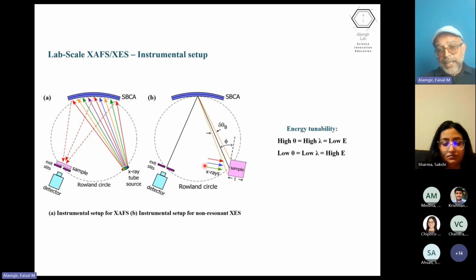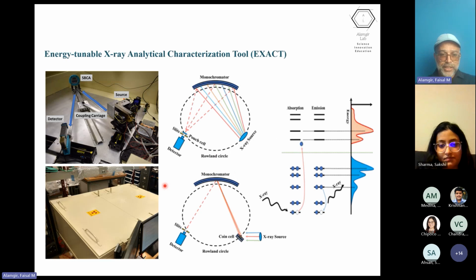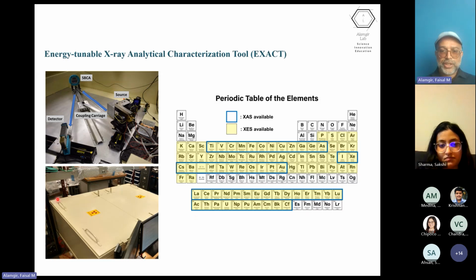Similarly, if we irradiate the sample directly with an X-ray source from the outside first, and then look at all the X-ray emissions coming out of your sample, we can use that same crystal to energy select the emissions coming from your sample, and then we can do high energy resolution X-ray emission spectroscopy. So that's basically what we can do in this instrument that's pictured on the left. Using this, we can essentially get analytical measurements from this swath of the periodic table currently.